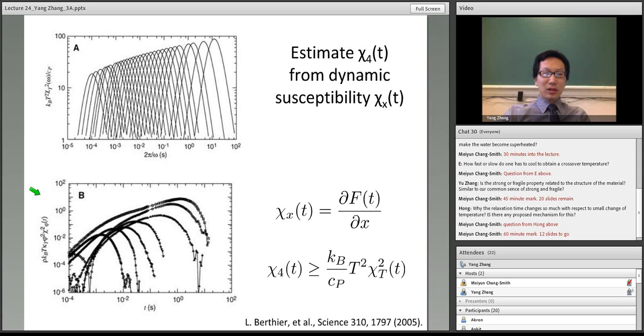Another disadvantage of this method, or maybe not a disadvantage, but a concern, is that this inequality relies on the fluctuation dissipation theorem, which is known to break down at certain temperatures when approaching the glass transition. So this kind of description works in the supercooled regime and maybe even near the crossover temperature, but eventually this kind of formalism may break down. So it is a big challenge how to really quantify the 4-point correlation functions directly from scattering experiments. Okay, all of those are open questions.